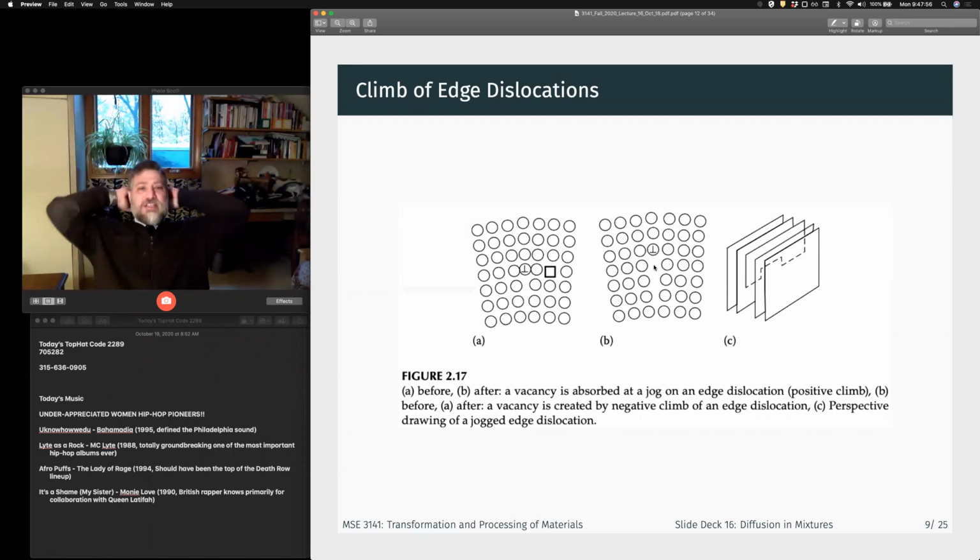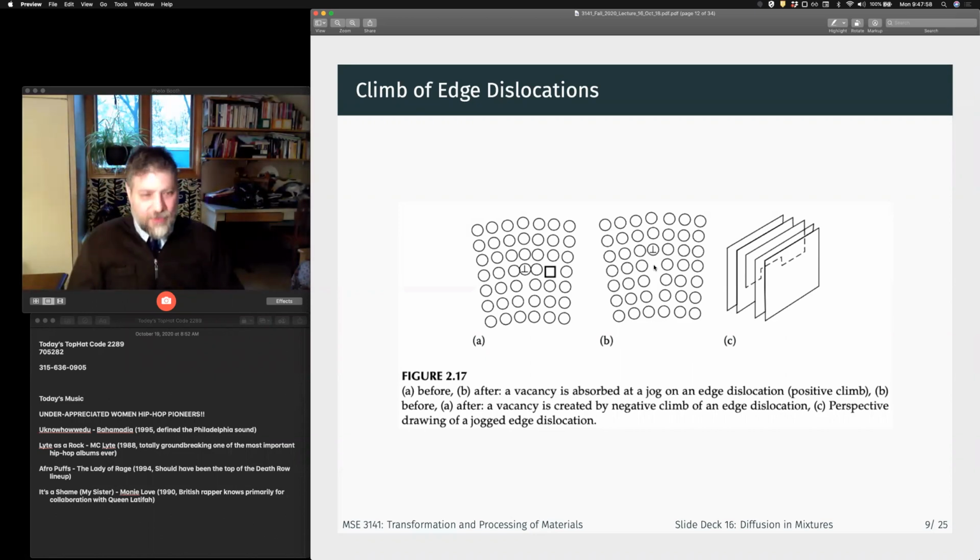What's the dislocation density in a heavily cold-worked sample? If it's cold work, there's going to be a lot more dislocations because that's the process of cold working. It causes dislocations to harden the grains. Yeah. Right. So the upper limit that you can reasonably reach is about 10 to the 16th, right? About 4 orders of magnitude higher. Right? So how long is 10 to the 16th meters?